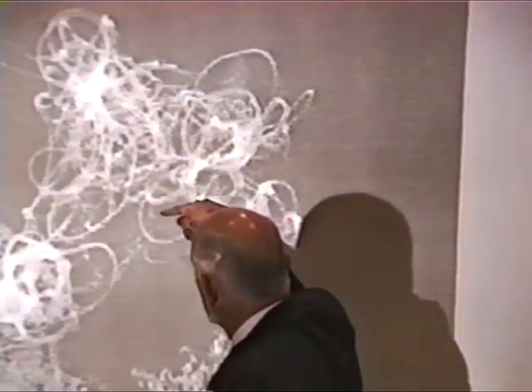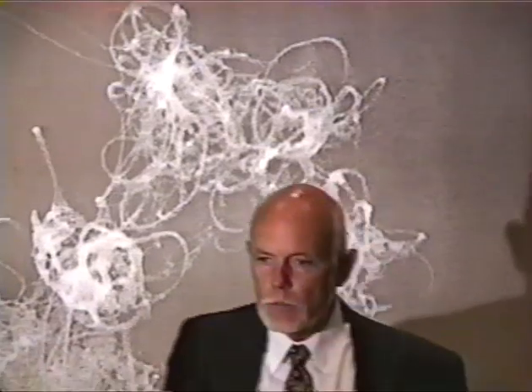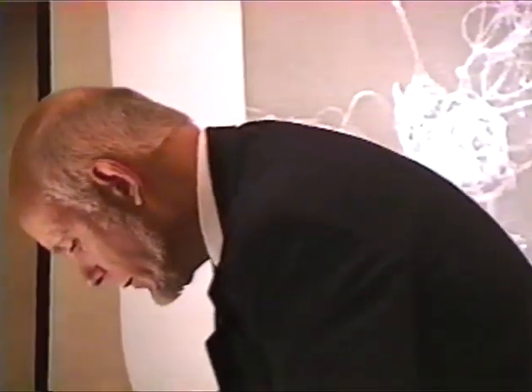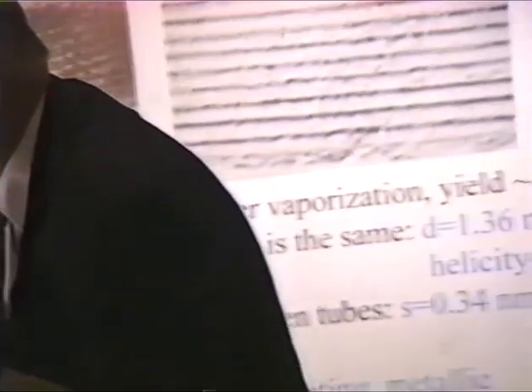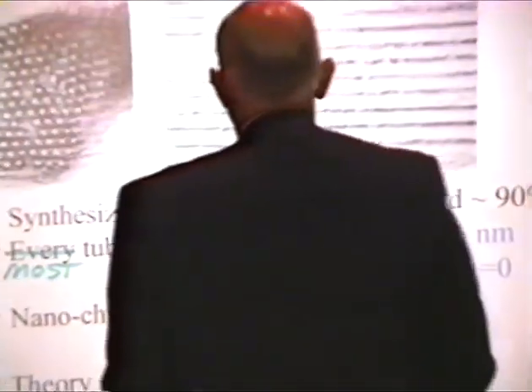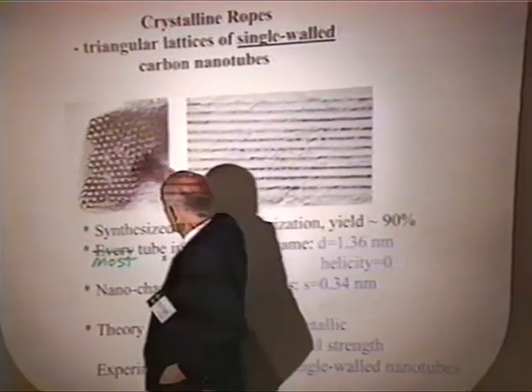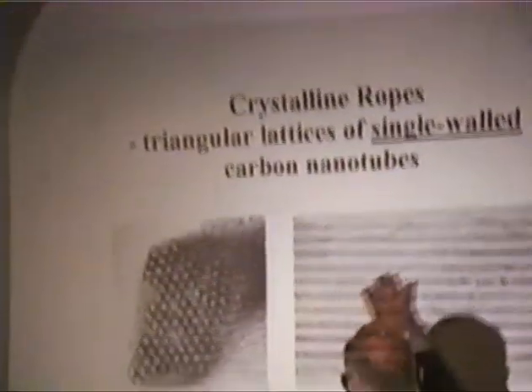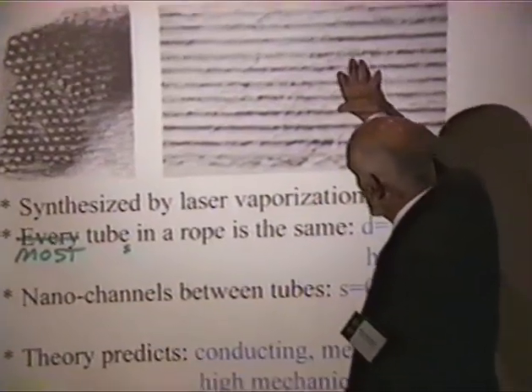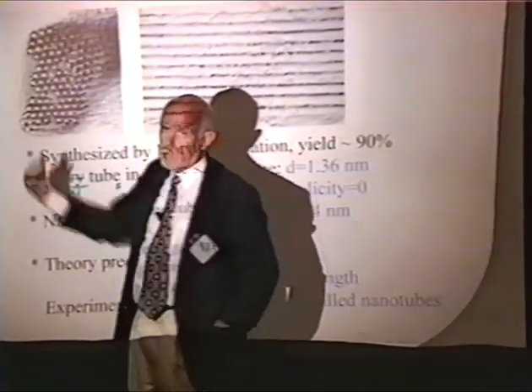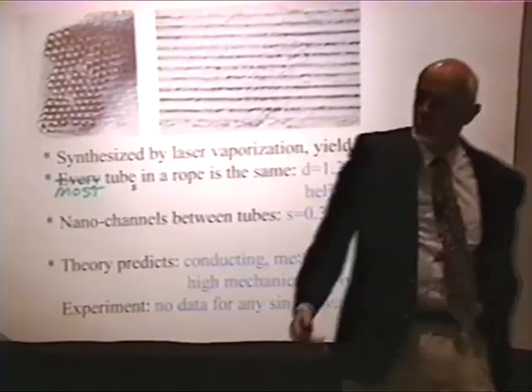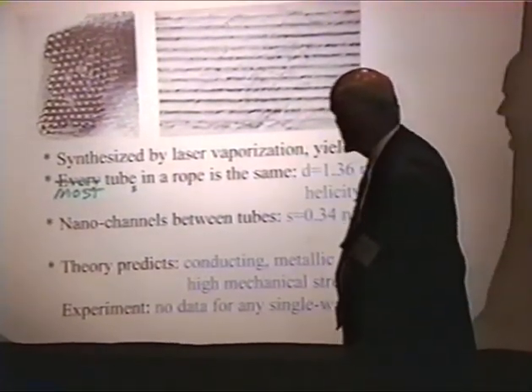And these fibers here that you see in this raw material, we call it a felt, are actually not individual nanotubes, but rather they are constructed of hundreds of individual tubes. I'm looking for, here we go. So if you look at the side of one of these fibers, you'll find that there consists of, in this case, well over 100 individual tubes. You can see them along the side of the rope here, or what appears to be the end, but this is really a rope of these carbon tubes bending through the field of view of the transmission electron microscope.